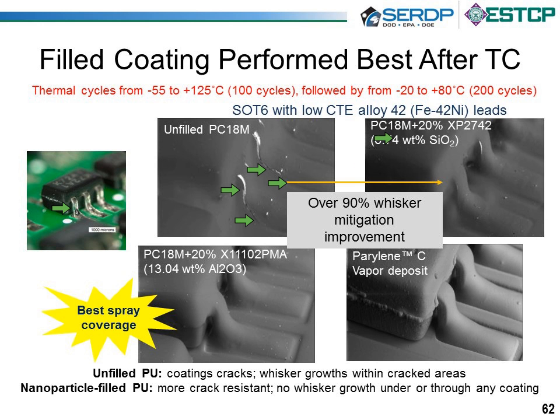With the nanosilica, we didn't see any crack formation over the same environments. As coated, it had a little bit of thinning on some of the corners, but far less than what we saw with the unfilled coating. And the nanoalumina looked like it coated the best. So wouldn't you have it that the non-functional material yielded the best coating coverage, even though it may not have optimal mechanical properties, but it had excellent coverage during the spray coat.